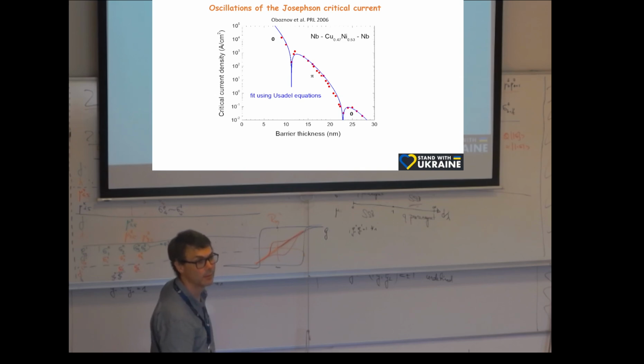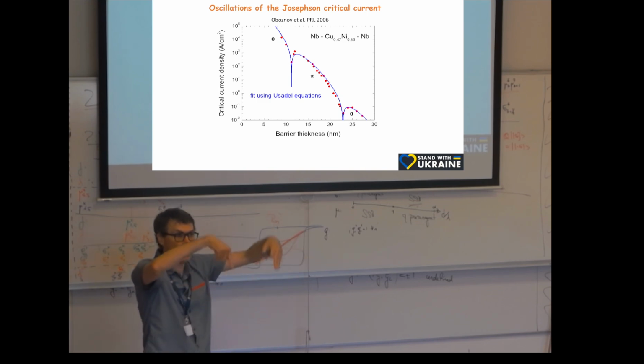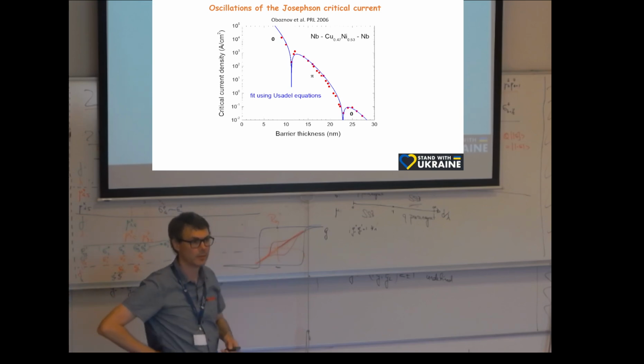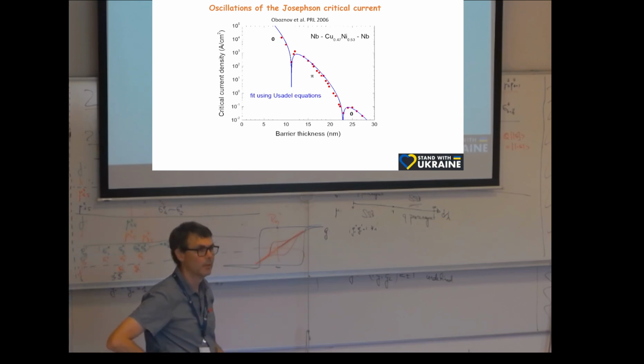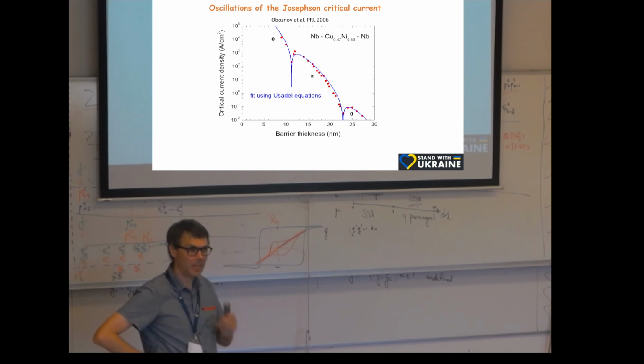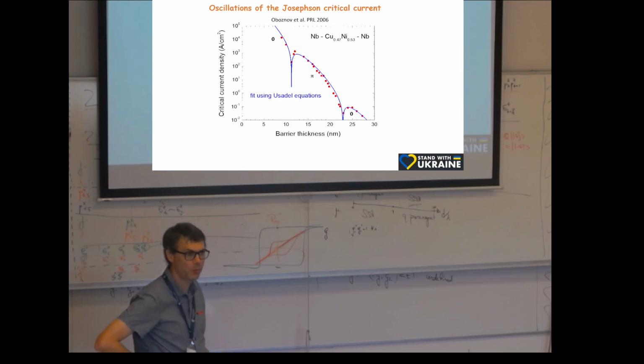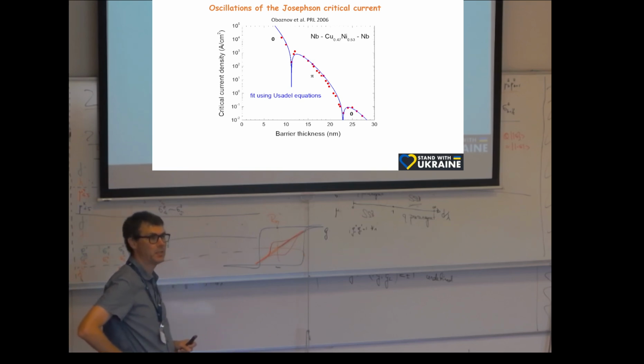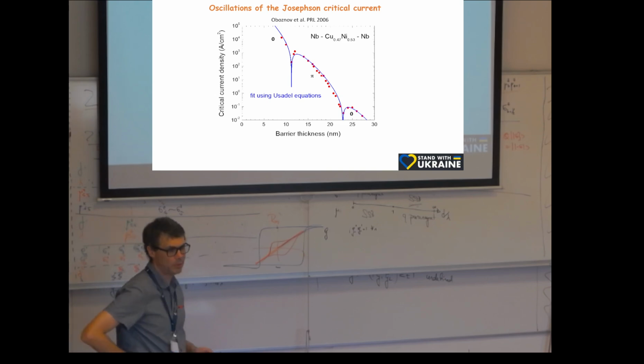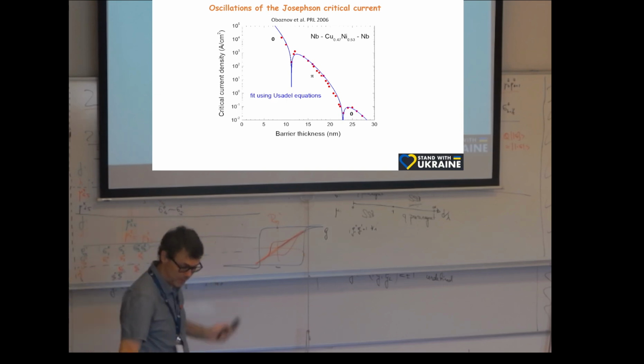You say this is a very large junction, like 50 microns. That's the area, right? And this tunneling direction is 30 nanometers. So how well can you maintain the thickness of this area? Good question. So I have some slides about that. It's not perfectly smooth, but apparently it's quite smooth. Yeah. So my fit to some model gave sort of 1 angstrom variations. But this wasn't the samples. So some magic samples.